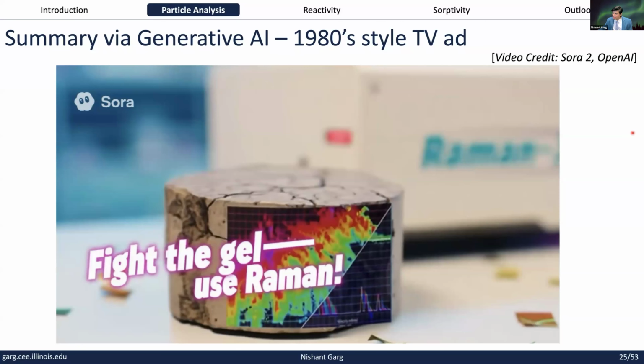Okay, so the first question is from Shikhar. You compared it with SEM, but because it uses visible light, won't it have a worse resolution? Yes, indeed. If you compare Raman spectroscopy or Raman imaging with SEM, it does have a worse resolution. The best resolution that you can get with Raman is on the order of 350 nanometers, or just less than half a micron, whereas with SEM you can get a resolution of a few nanometers.